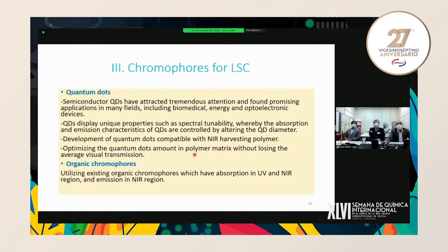So if we optimize the quantum dots amount, concentration actually, we don't lose the average visual transmission. If a higher amount is added, then we lose the average visual transmission. Another one is the organic chromophores. So we'll use the existing organic chromophores, which have absorption in UV and NIR region and emission in NIR region. So if you combine both these quantum dots and organic chromophores, like a tandem or hybrid system, then we can increase the efficiency of our transparent LSCs.